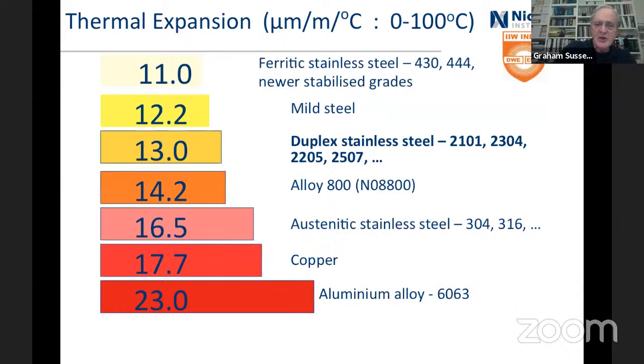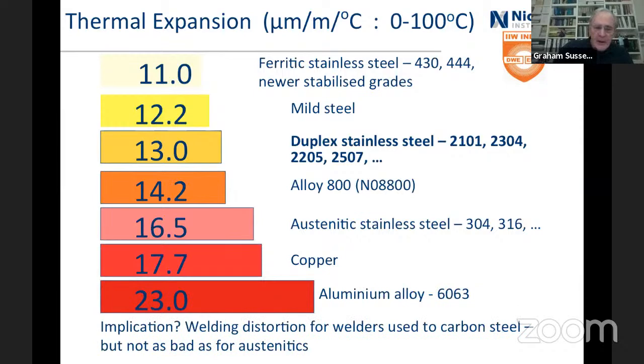Looking at thermal expansion, just other bits and pieces. Okay, where's our austenitics? Here up at 16.5 compared to 11 for ferritic stainless steels or 12 for mild steel. And duplex is sitting down nearer to the mild steel. So in fact, if you can deal with the thermal expansion of mild steel, then you can deal with the thermal expansion of duplex. Whereas if you're dealing with austenitics, then you've got to be a lot more careful. So if somebody can weld with austenitics and not have distortion problems, then duplex shouldn't be a problem for them. There are just other problems.